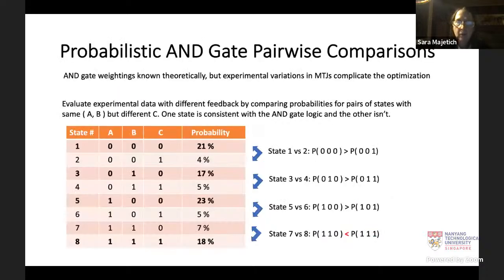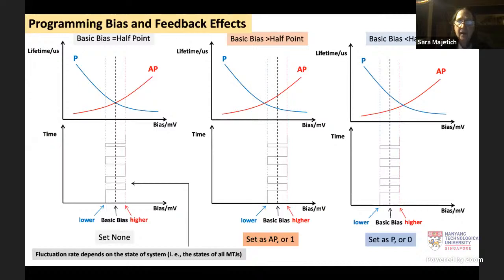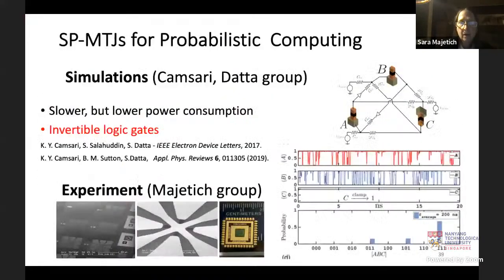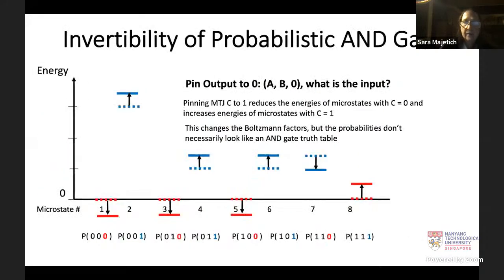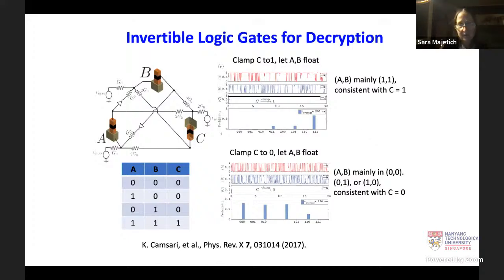Then you go back and you take one of those tunnel junctions, the output, and you ramp up the bias, pin it to the anti-parallel state, or ramp down the bias, pin it to the parallel state. So go pin it to a 1 or a 0. And that's going to effectively change the energies of those microstates. So if you measure your system free running, then pin the output, you can work backwards, and by looking at the statistics again, looking at the differences pairwise, you can figure out what the likelihoods of different values of A and B for an output C equal to 0 in this case, or C equal to 1. So that's the way this process works, and could be used for decryption.